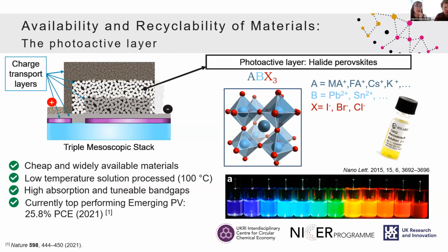And at the moment, they're the top performing emerging photovoltaic. I think it's at 25.8% of efficiency as per 2021. And this is very, very close to lab scale silicon devices. So let's say the top silicon, I would say, probably stands around 27%. And the 25.8 is pretty good considering that perovskites were born pretty much like 10 years ago. And then lastly, last but not least in this case, they're inherently recyclable because, well, they're easy to make and easy to break. They can be redissolved into an ink. And now this last one, easy to make, easy to break, we'll have to think about it as well later on, but I will discuss more about this.